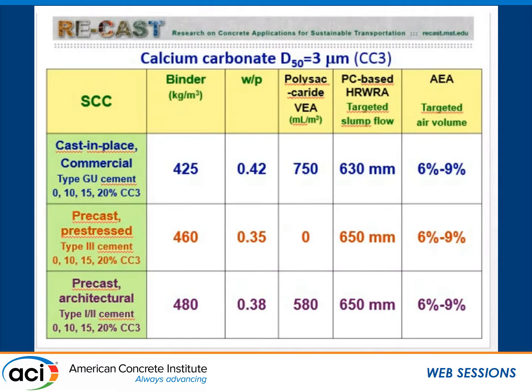So the first one is for commercial applications. We use a type GU cement or type 1 cement, and we had replacements of 0, 10, 15, 20. What Eric was saying, 15% is very typical. Again, this is before the GUL, so we're talking about 10 years ago. And the content of cementitious materials was 425, which is about 720 pounds per cubic yard.